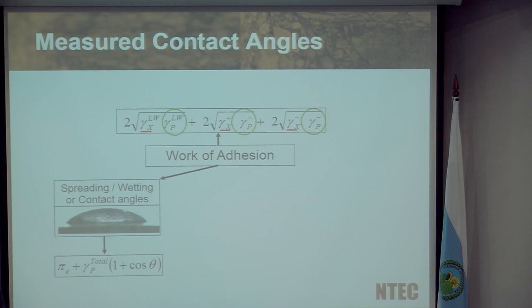The advantage, though, is if we look at exactly the same equation now, we don't have any atmospheric pressure. This test is done at room temperature and in a normal atmosphere. So there is no pressure that's been applied in terms of the test. So straight away, your spreading pressure, which was a key criterion for the aggregates, is no longer applicable. And therefore, the only unknown now, if we choose our probe liquids with known energy parameters, is the contact angle. And contact angles are easy to measure. And I'm going to show you two different techniques that we've used at Nottingham. I know that you've got the facilities here at the university to measure at least one of those in terms of working out contact angles.